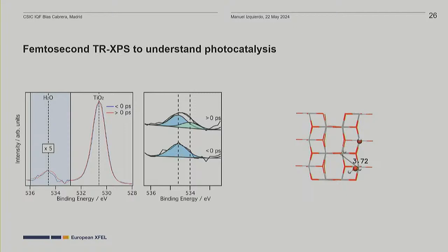And so what you can see here, when you multiply the water part by a factor of 5, is that there is a broadening of the peak and also a movement toward lower binding energies. And so this implies that there is a second component that is formed. Then the group of Angel Rubio did some Ehrenfest simulations to understand what's going on with the system.